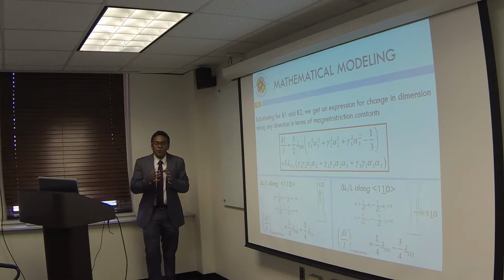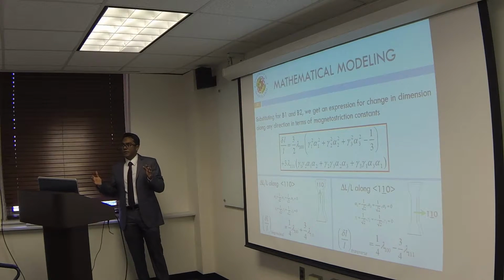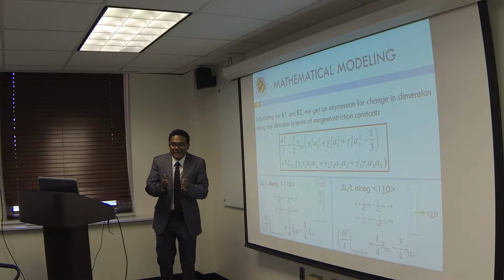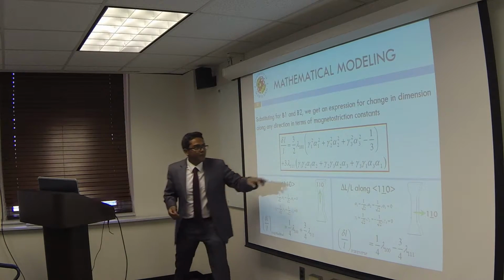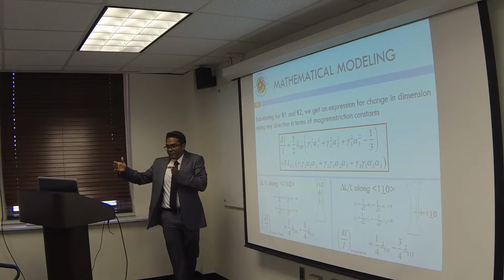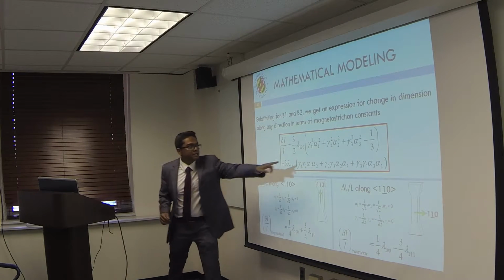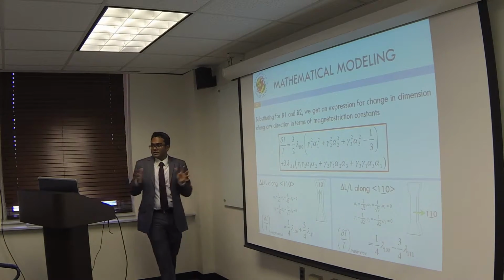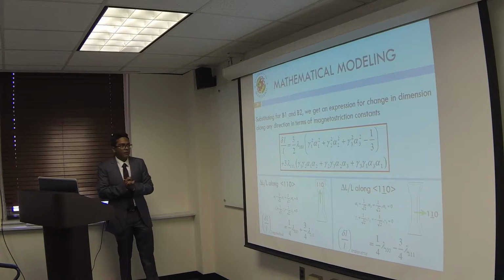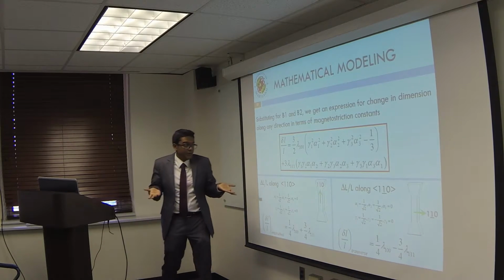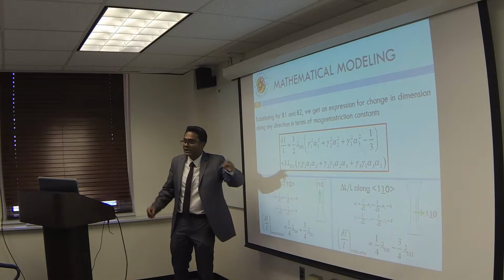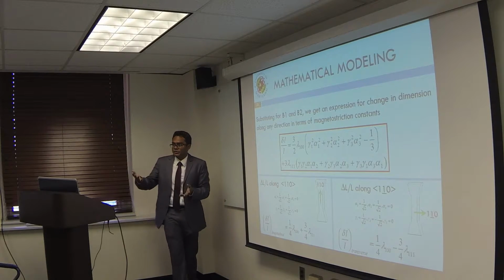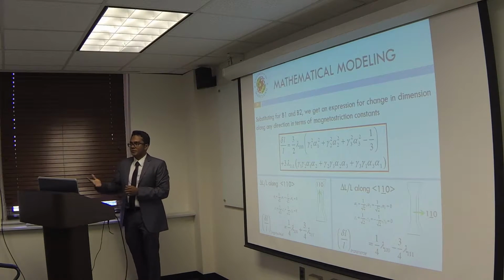which tells me how much strain I can get along any crystallographic direction for applied magnetic fields along any direction defined by gamma, and I can measure the strain along any direction defined by alpha. So this is really neat for me to be able to calculate the strain along the direction that I'm interested in, which is the 110 direction, and the perpendicular 110 direction, which is called the 11 bar 0 direction.